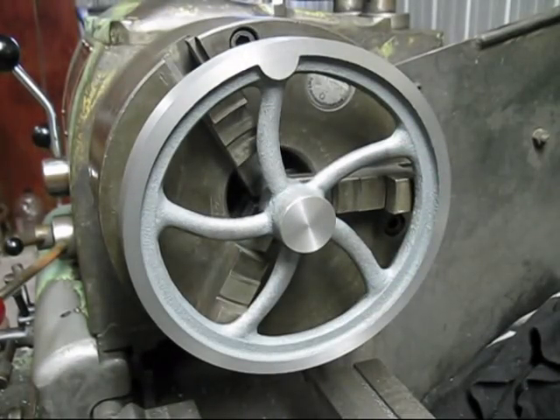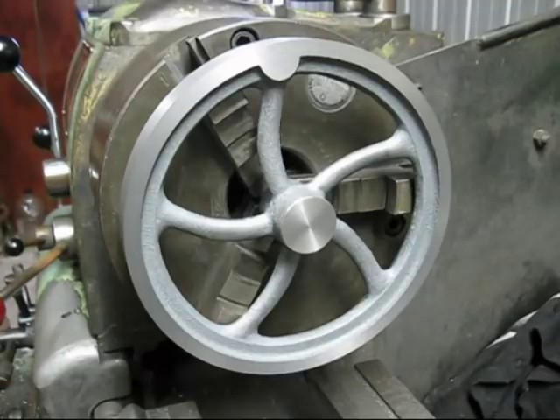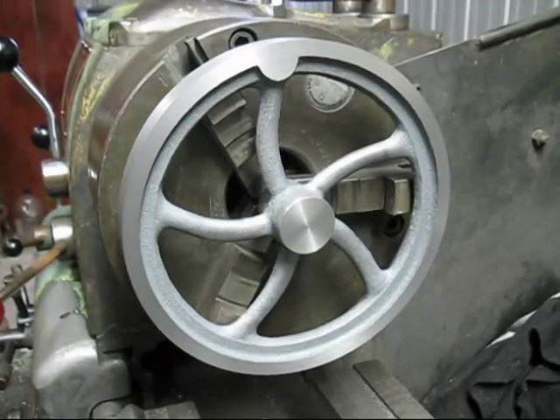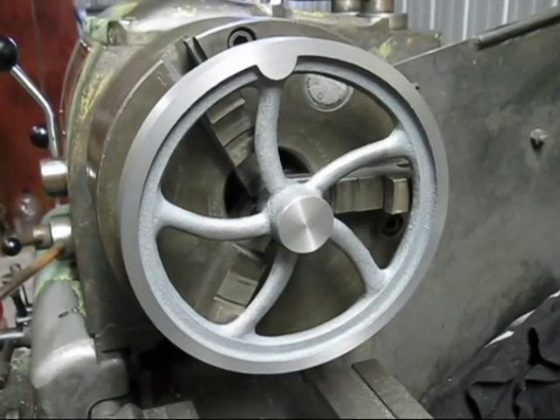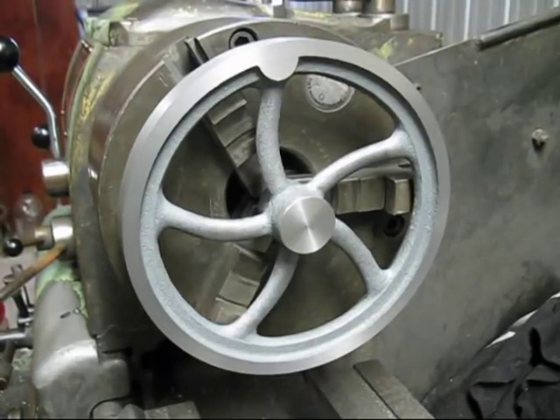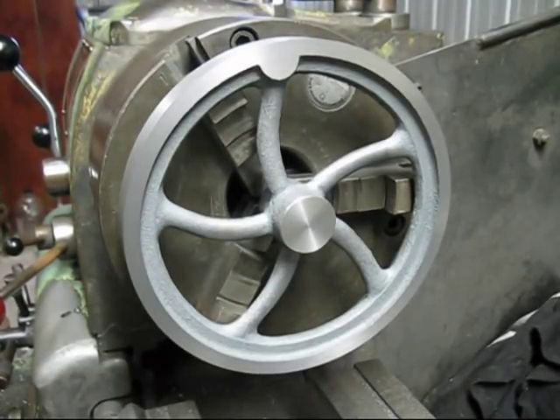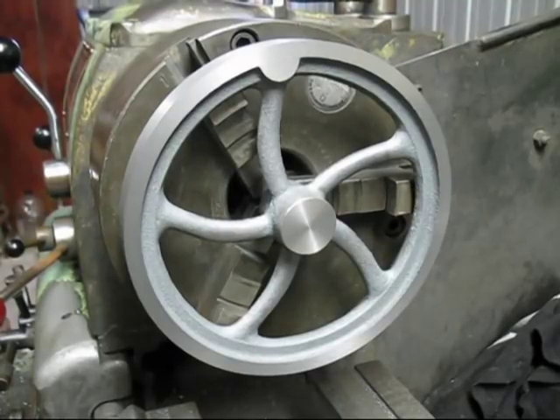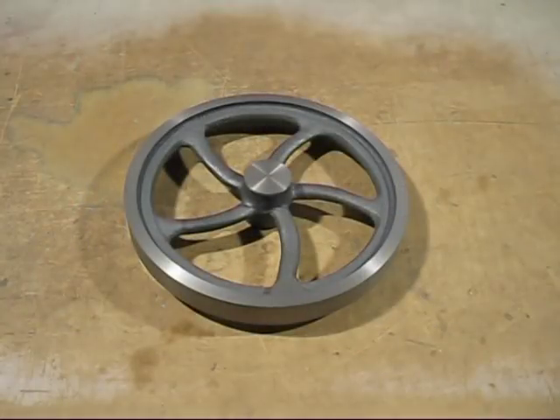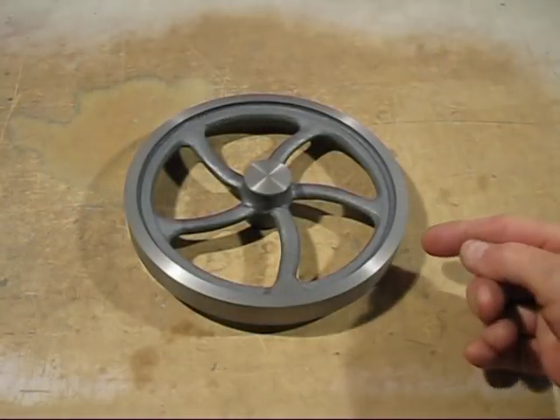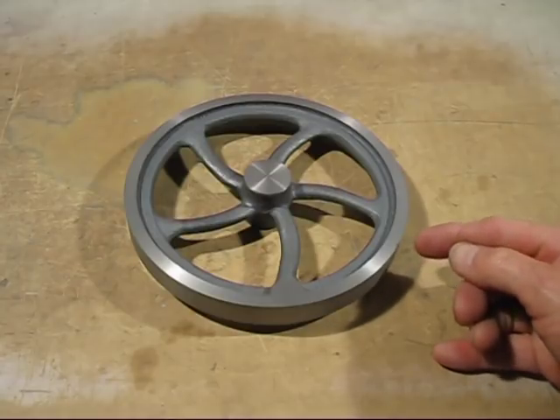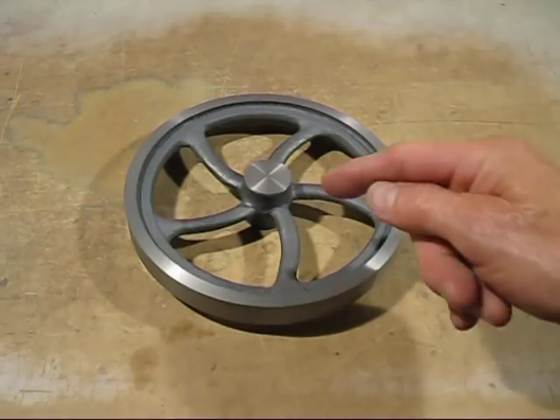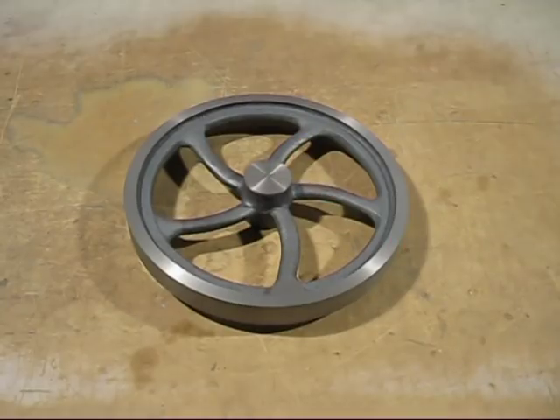I've finished machining, so now what I've got to do, I've got to check very closely where it was gated and see if there's any shrinkage cavities or blowholes or any inclusions. And they will show up as holes in the casting. Here is the casting. It's all been machined up. So I've machined it up on the rim, on one face here, and the top of the boss. And it machines really great.